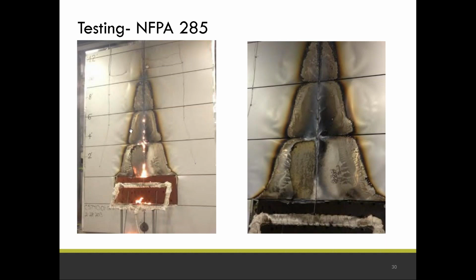One thing about this particular picture I like to point out is you see this buckling here of the top skin. The fire retardant, the mineral that's used in the core is actually a fire retardant. It actually turns into steam and aluminum oxide at about 400 degrees. So in doing that, it actually buckles the skin a little bit, but it also cools the fire.